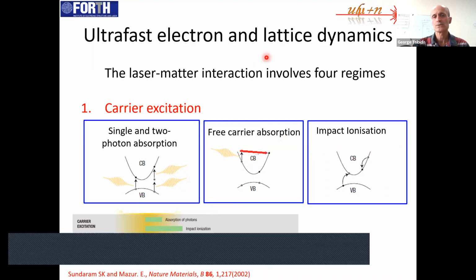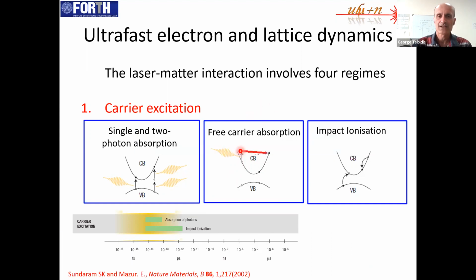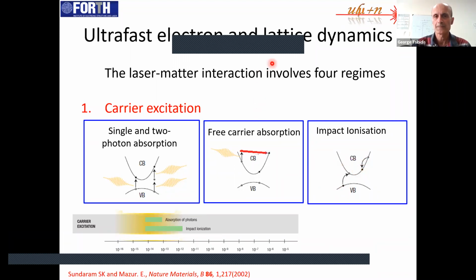So we assume, for example, this situation here, that we have a free carrier absorption. So we have carriers which are already in the conduction band, and when they absorb energy, they just move inside the conduction band to higher energy levels, but we don't increase the carrier density through this process. And of course, we can have a third regime, the impact ionization, when we have this scheme: the energy of the electron in the conduction band is big enough so that when it collides with an electron in the valence band, it excites that one into the conduction band while the former one stays in the conduction band as well.